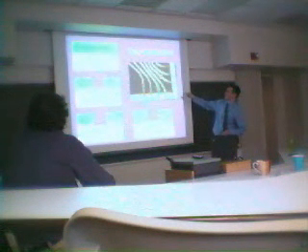The fabrication of this was somewhat tricky. This is a really zoomed-in view of the T-trap, and this is its top ceramic layer with these gold wires on it. And the tricky part was that in this corner here, these wires are pretty thin, about 50 microns at its narrowest point. And so we couldn't just use a metal mask, physical mask, to lay these lines down. We actually had to do photolithography on that.